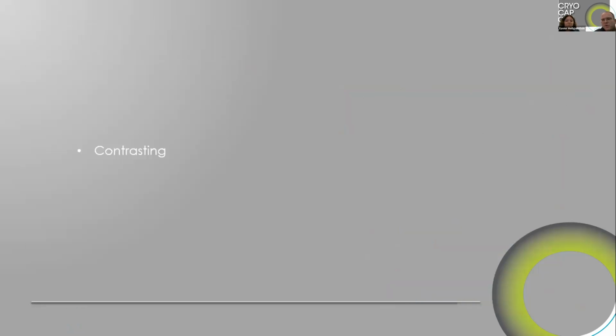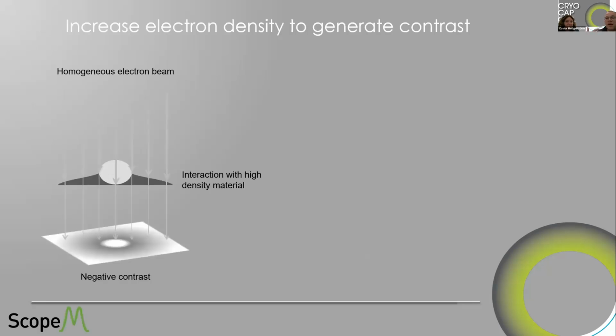Then the contrasting. The contrasting is something very, very important because our proteins are made of CHO, and our resins are made of CHO, carbon, oxygen, hydrogen. And so basically, there will be no difference in mass, and so no difference in contrast under the electron microscope. So that's why we add some contrast by bringing some heavy metal salt that will interact with the proteins, go inside the cavities of the protein, and remain there so that when the electrons are hitting the heavy metal, they will be stopped or diffracted, causing a differential image on your electron microscope screen.